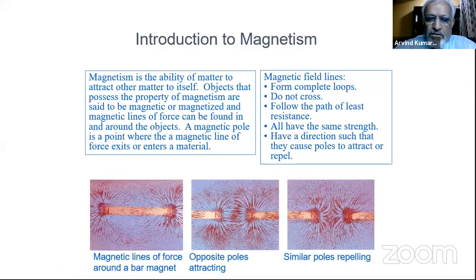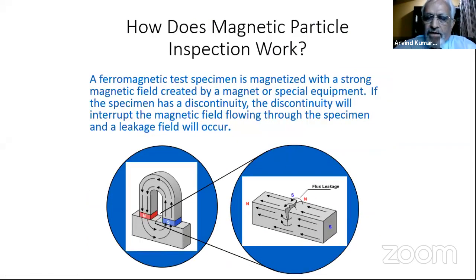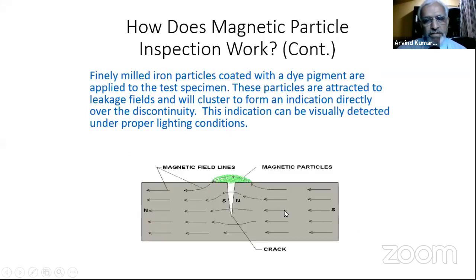Now, when you're magnetizing a part, you can generate either a longitudinal magnetic field or a circular magnetic field. And when there is a discontinuity, the flux introduced because of magnetism will leak at the points where there is a crack or opening, and the flux lines will jump over it. When you apply a magnetic ink or a dry powder, it will get attracted because of the changes in the flux density that is formed. See, here you can see where there is no discontinuity or imperfection, the flux lines are moving smoothly. And where there is a leakage or a cavity, the flux lines get concentrated. We'll see in the next slides where you will be able to find a defect.